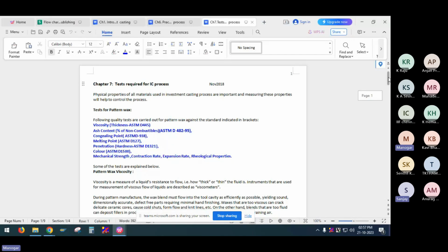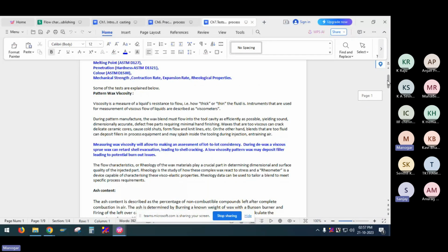And we go through what the tests are, how they are done, and why they are necessary. Viscosity is a measure of a liquid's resistance to flow, how thick or thin the fluid is. Measuring wax viscosity allows an assessment of lot-to-lot consistency. We make different batches, so we need to maintain this consistency. We have to measure it, and only then can you get a proper wax pattern. If viscosity is not maintained, a more viscous wax will crack the shell during de-waxing, and low viscosity wax will deposit in the filters and affect the surface finish.